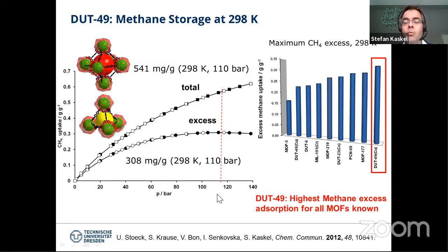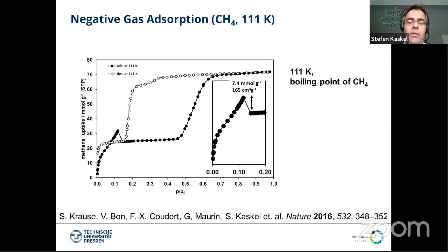So initially we invented this material for our gas storage studies. So this is a high pressure gas storage experiment up to 140 bar. And this was the world record in 2012 in terms of gravimetric gas storage capacity, up to 540 milligram per gram storage capacity at room temperature. And at that time, we became more interested in studying the fundamentals and why this MOF is so special and has such a high capacity for methane storage.